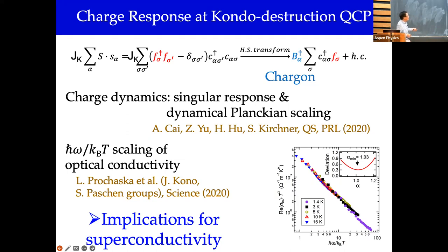So this is a very interesting statistical mechanics perspective on how quantum entanglement mixes up with quantum criticality, but it also has important implications because spins are the main agent. These are the building blocks that are driving this quantum criticality. You have a very large number of degrees of freedom. As a matter of physics, we like to count degrees of freedom. Everybody should count the degrees of freedom in terms of entropy. So there's R log 2, or almost R log 2, 50% of that, associated with the critical fluctuations. But it lives in the spin sector. But if the charge sector is also picking that up, we could possibly now think that it's connected to superconductivity, to this holy grail of the mechanism of superconductivity.